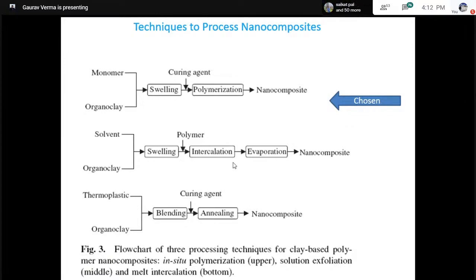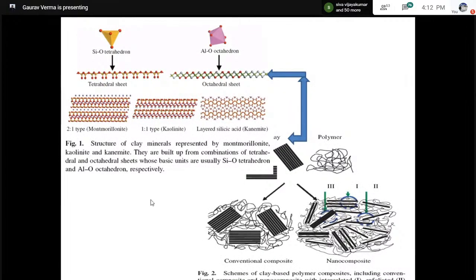Now, if you are working in research areas in nanocomposites, you would understand that synthesis is really a daunting task which has to be given due weightage. Because if you don't do that, you do not end up making a nanocomposite. So this slide is actually showing you the physics and the chemistry of how a nanocomposite is formed. This polymer chain, which I'm showing you with a cursor, if it does not enter, let me remind you of the same image I had shown you, wherein at 1 micron you saw a large size non-crystalline, maybe a satellite or a UFO-like image. You did not realize that each clay platelet has a nanoscale feature. It's a nanoplatelet, and that cannot be done if you're not using the correct synthesis technique.